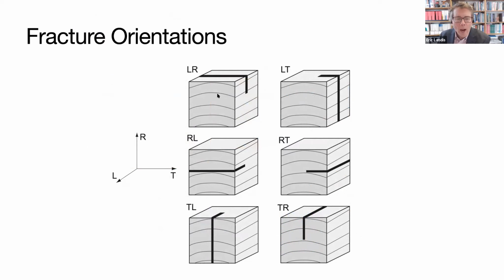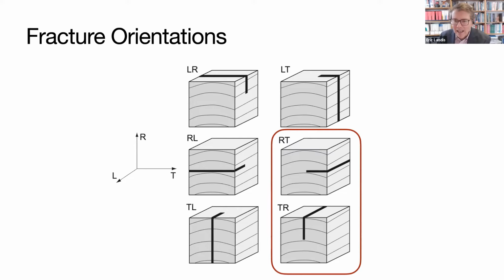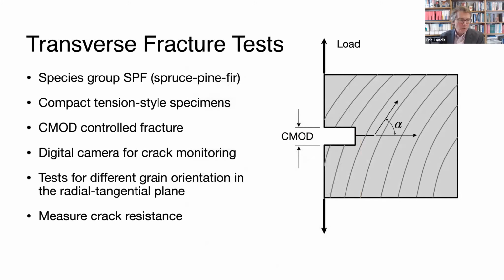So just one more primer. For the notation used for wood fracture, we use a two-letter system where the first letter indicates the normal of the crack plane, and the second letter is the direction of crack growth. So in the case we're looking at today, we have RT and TR and some variations of the two. In RT, the crack plane normal is in the radial direction, and the crack growth is in the tangential direction. So I'm just going to generally call this transverse fracture.